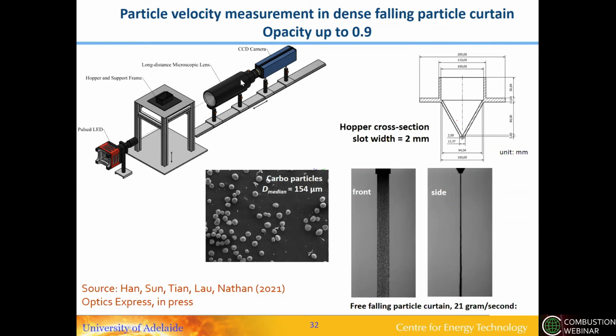Effectively, a backlight is put on one side of the particle system that you want to measure, and on the other side, a long-distance microscopic lens. Ziwei Sun from our team has done most of the driving of this technique development. Here we're showing it being demonstrated on a falling curtain of particles, which is also related to the work on the solar concentrator that I mentioned earlier. In this case, the particles are carbo particles of about 150 micron in diameter. This curtain is a two-dimensional slot of about 2 millimeters thick, although we're also now applying it in significantly thicker curtains.